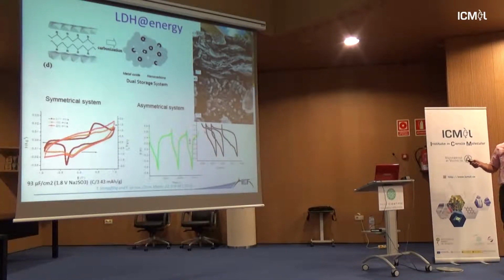So we end up with some carbon and small particles that you don't want to get rid of because they are potentially electrochemically active. So you may have some Faradic process if you go slowly enough in cyclic voltammetry. You can see that here it's 0.1 millivolt per second. You can see the Faradic process because it's a slow electrochemical process. You have to oxidize and reduce. So it's a redox activity. It's not only a surface activity.